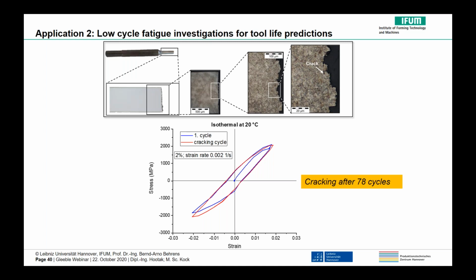When the LCF test is performed at room temperature, the sample is only subjected to mechanical stress. Here, the main mechanism for sample failure is pure fatigue. Due to dislocation movements caused by the load change of tensile and compressive stresses, cracking occurs in the forming zone and the material fails when the critical crack length is reached. So in this case, cracking occurred after 78 cycles.